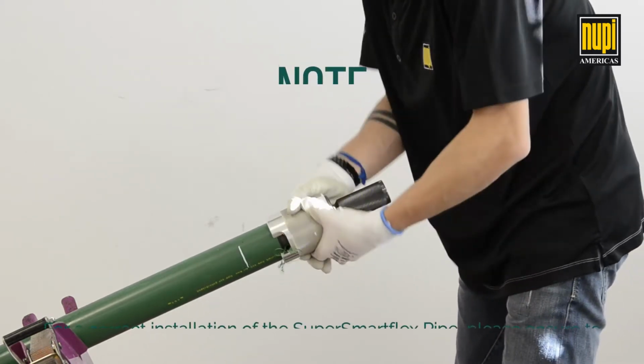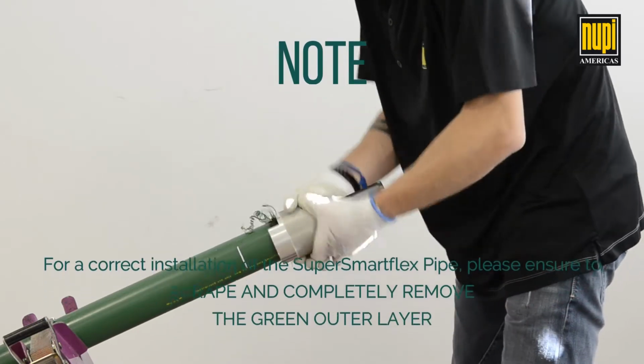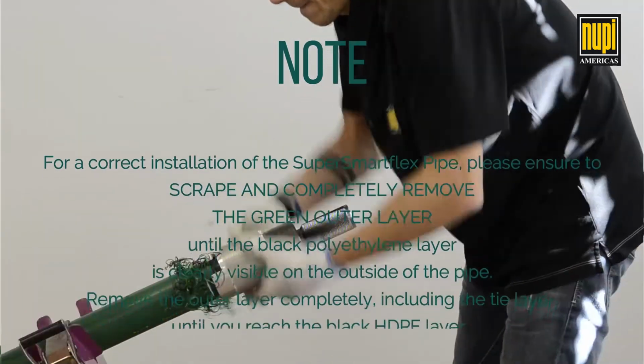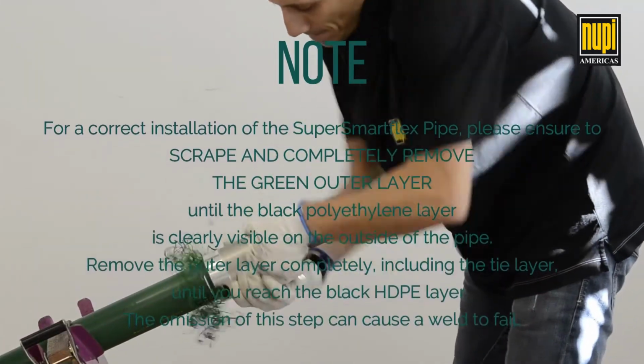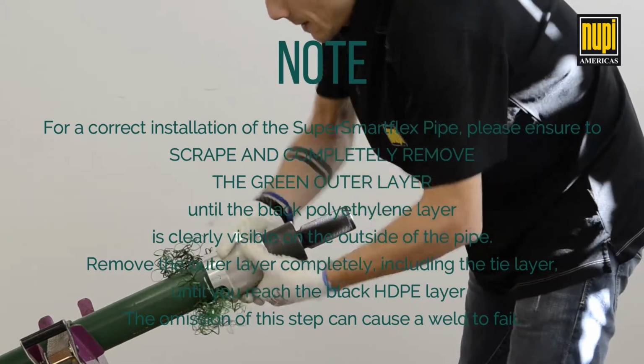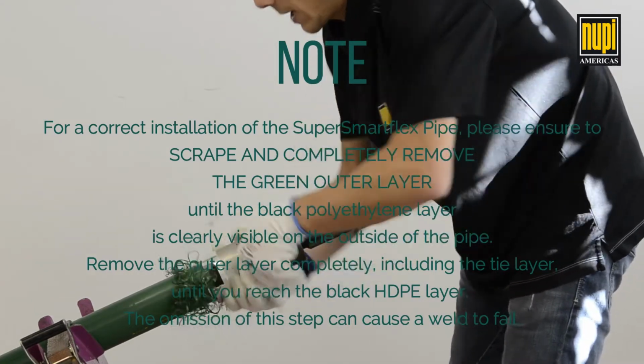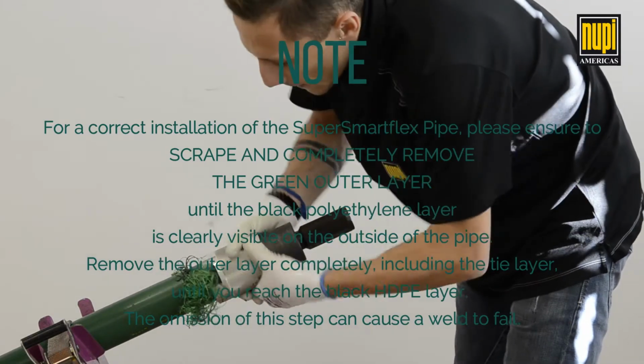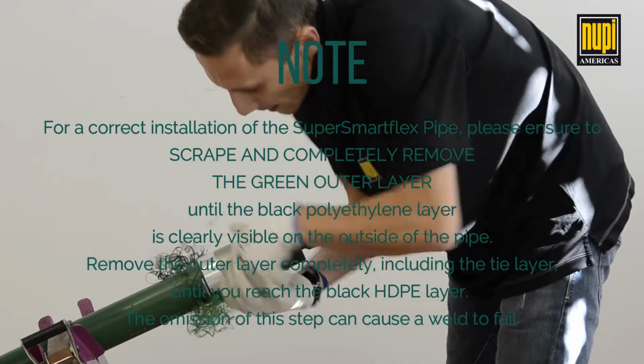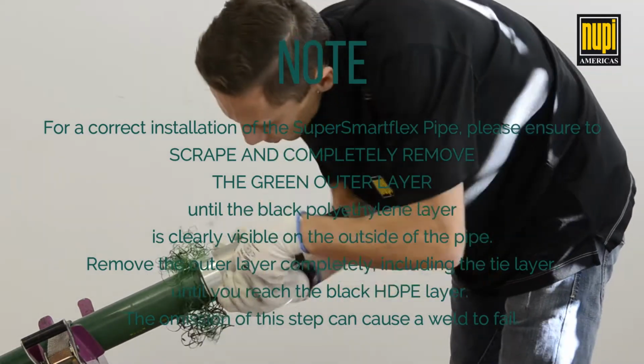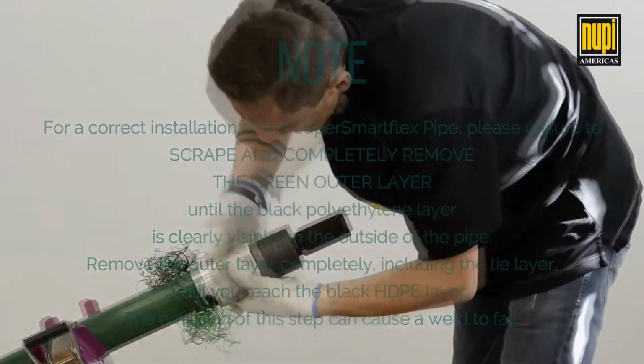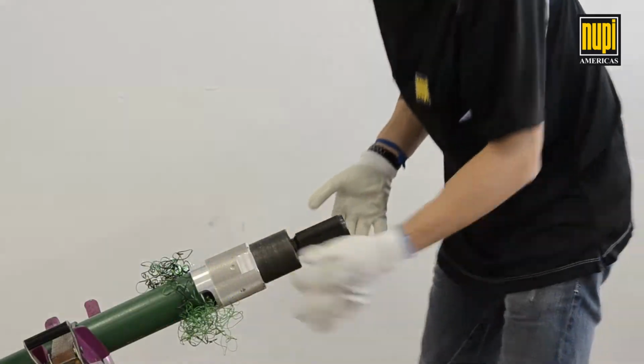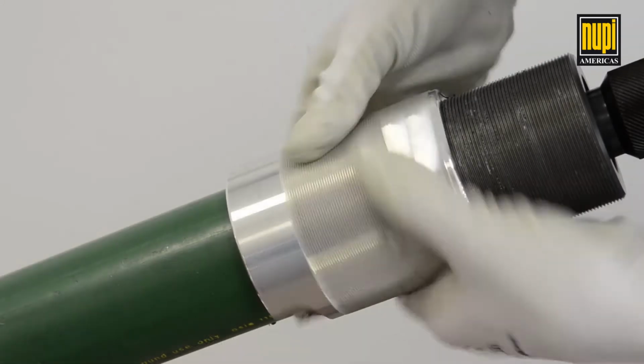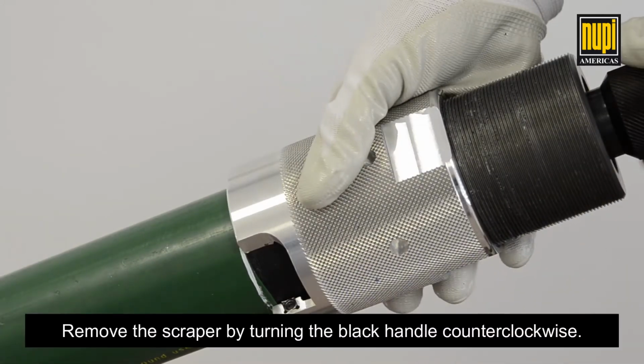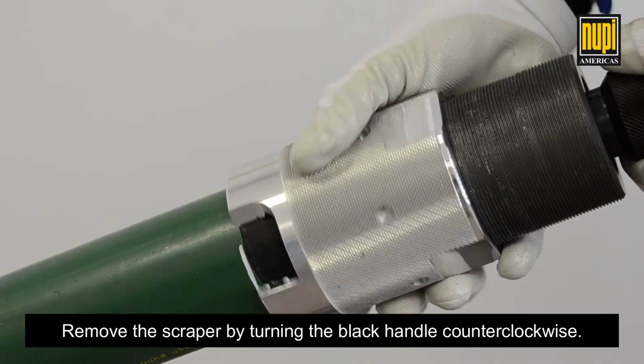For a correct installation of Super Smartflex pipe, please ensure to scrape and completely remove the green outer layer until the black polyethylene layer is clearly visible on the outside of the pipe. Remove the outer layer completely, including the tie layer, until you reach the black HDPE layer. The omission of this step can cause a weld to fail. Remove the scraper by turning the black handle counterclockwise.